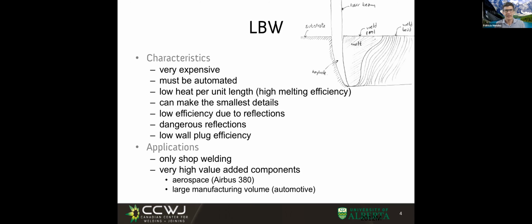Even in automated cases, the reflection of the beam can come back. A funny thing: if the beam is aimed against a flat surface, the reflection can come back in, and the laser would be committing suicide, killing itself with its own power. That's the reason why in many laser operations, when you weld on a pipe, the laser is a little bit off center. So if there is a reflection, it doesn't come back directly into the laser.